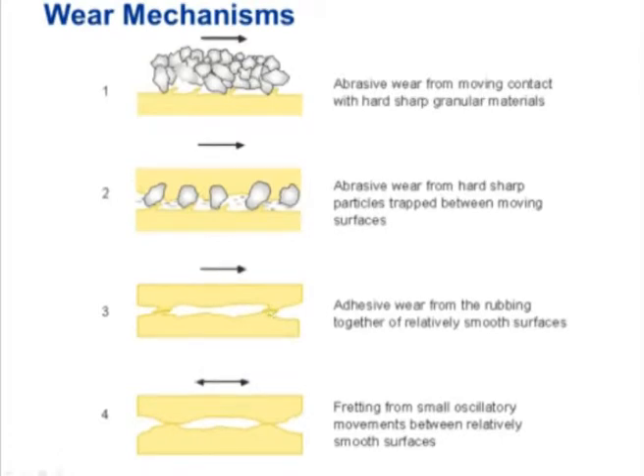Moving on, adhesive wear. This is where you get one nominally flat surface moving over another. One of the important things to realize is that even though you think it's flat, it's not really flat, and typically between two surfaces you get 4 or 5 different points that are carrying most of the load, and at those points you can get phenomena like welding of the asperities together, and then you get removal of material and you get wear processes that take place. Fretting comes from small oscillatory movement between relatively smooth surfaces, but the emphasis on this one is that it's small motion.